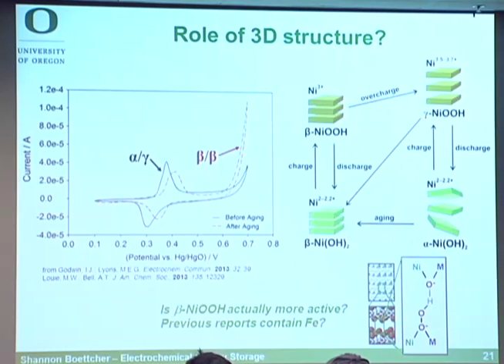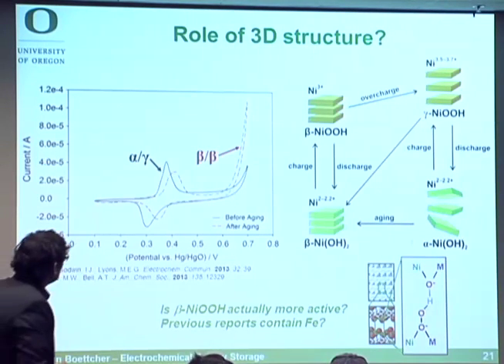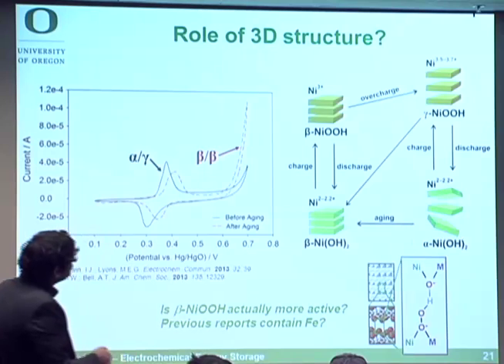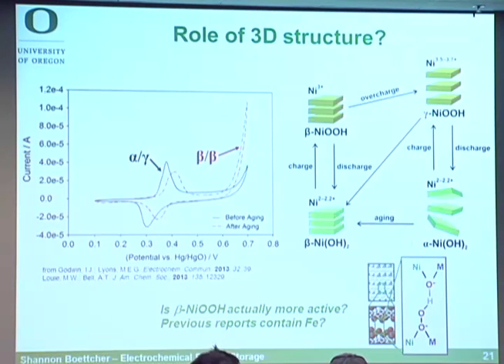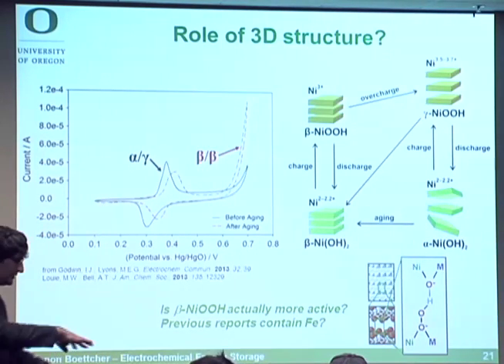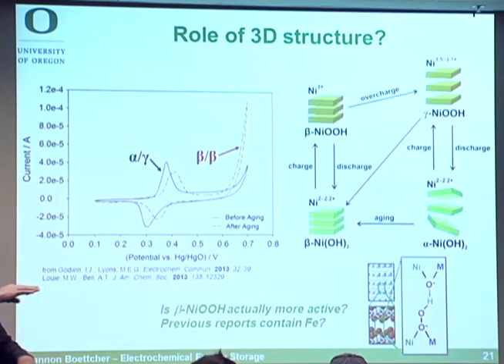Okay, so we wanted to test a few things. So one of the things we wanted to test was the role of structure. So this is from the battery literature. As you precipitate, you form nickel hydroxide, you get this alpha phase. You have disorder between the sheets in the three-dimensional structure. And if you let it sit in the electrolyte for a while in KOH or heat it a little bit, it goes to this beta phase, which is basically more ordered, and it's the structure I've been showing you.